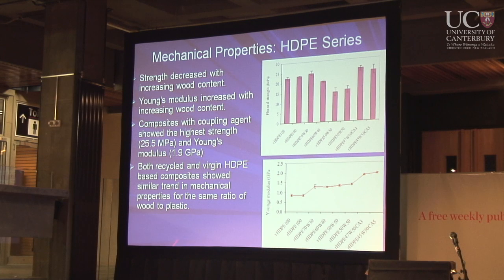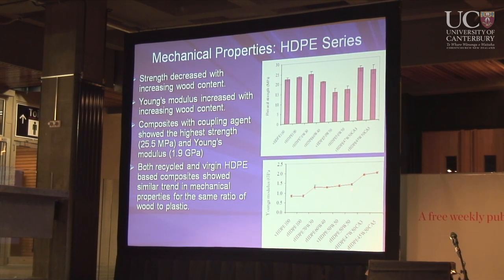And the stiffness, this is the stiffness. As I mentioned, we like the materials to be stiffer. For pure plastic, the stiffness is much lower. No surprise. If you try to bend the pure plastic, it's relatively easier. Is that right? If you add wood, the material is getting stiffer and stiffer. If you add a little bit of coupling agent, it's very stiff, the stiffness is very high for these materials. So if you look at the result, these are the formulations we want to develop, right? That gives you the best result for stiffness.